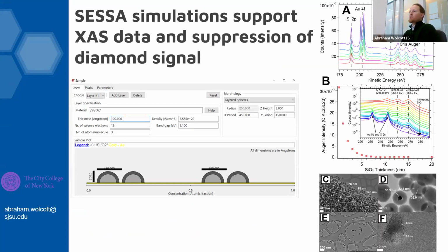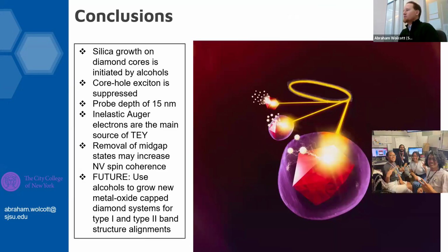We can go ahead and use SESSA, which was invented by researchers at NIST, to look at this Auger process and confirm that the thicker the SiO2, the less information we should get from our Auger electrons, which are here in the 240 to 270 range. And so everything was fairly consistent with this mechanism and the ability for these Auger electrons to be able to percolate up to the surface. When we look at the system, I think for the chemists in the room and for those who are interested in nitrogen vacancy center coherence times, it's really about the mechanism. But we'll just have these concluding statements.